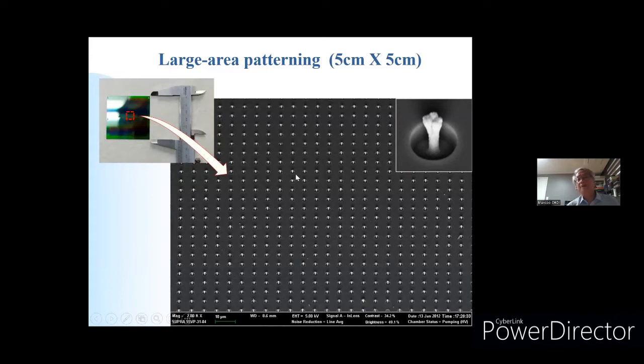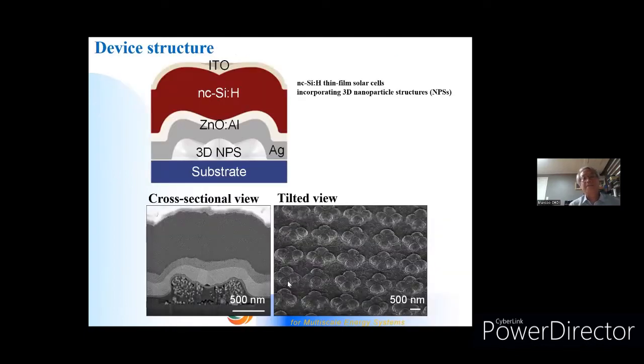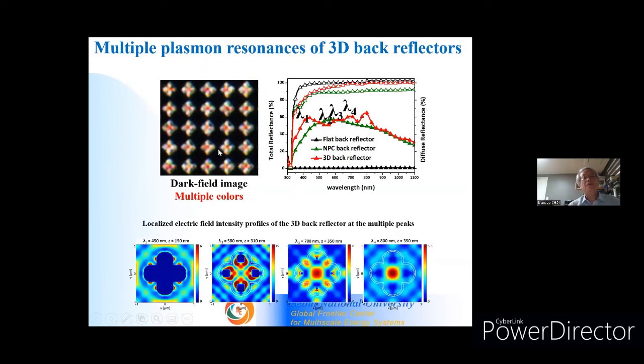And from this sample, we can now synthesize a silicon solar cell. This is our silicon solar cell applied with our 3D nanostructures. Of course, we also observed multiple plasmon resonances, several peaks.